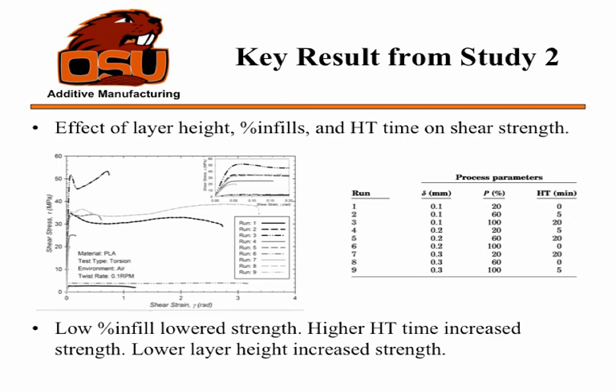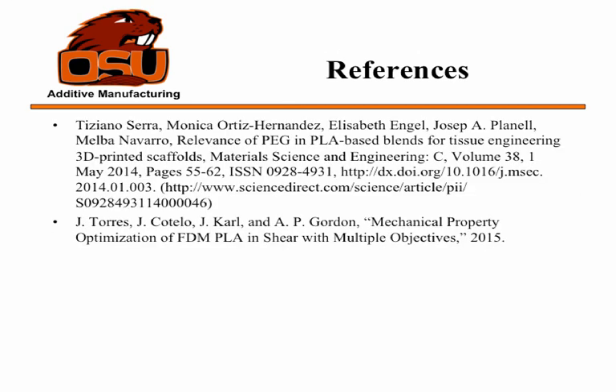and it actually makes it like 20% stronger than all the other polymers. It does make it more brittle, but typically PLA is brittle depending on how fast you load it. And then you can see down on the bottom there is run 1, which interestingly enough has the lowest layer height and lowest infill, but wasn't heat treated. It is actually weaker than most of the other ones. They did a Taguchi analysis, but I'm not too familiar with it, so I didn't include it. And those are my 2 references.